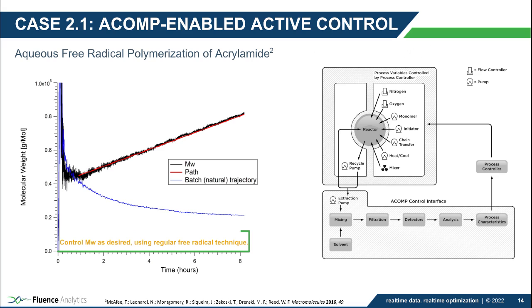The continuous nature of these quantities obtained with ACOMP is actually what enables a non-model dependent controller. Here, we present the first results of molecular weight control during acrylamide free radical solution homopolymerization. As we can see on the left, the molecular weight trend now was forced to resemble the monotonic increase seen for RAFT, which contrasts dramatically with the batch uncontrolled trend also shown on the plot.